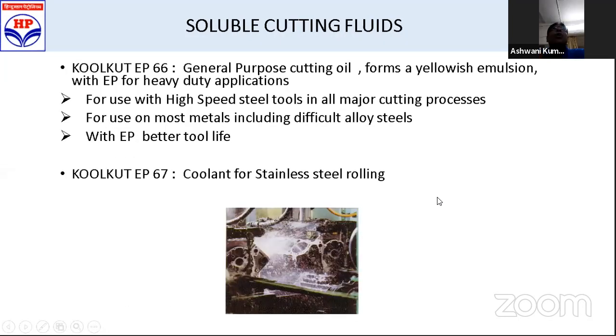And we have grades like Koolkut EP66 and EP67 with EP additives, that is extreme pressure additives, for where you need more severe machining and the depth of cut has to be higher. These are of course general purpose cutting oils. Again, 5% emulsions, but for heavy duty applications, and Maruti has been using it in the past. Koolkut EP67 is specially recommended for stainless steel rolling, where really severe machining is required. We in fact replaced Dubois of Netherlands at Jindal long back. This grade was promoted and accepted by Jindal. Next slide, madam.